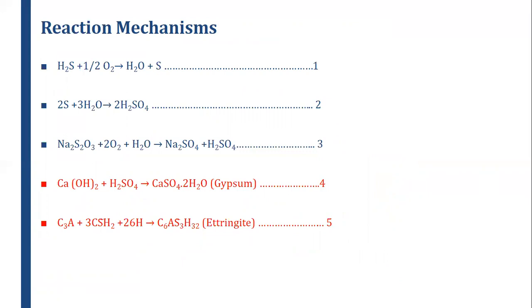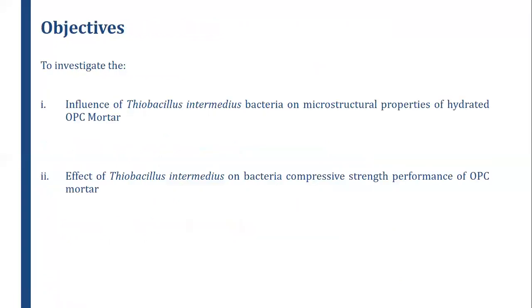Equations 4 and 5 show the formation of gypsum as a result of the reaction of biogenic acid with calcium hydroxide, and the resultant gypsum reacting with tricalcium aluminate within the concrete matrix to form ettringite. The formed ettringite is expansive and might result in cracking of the concrete structure.